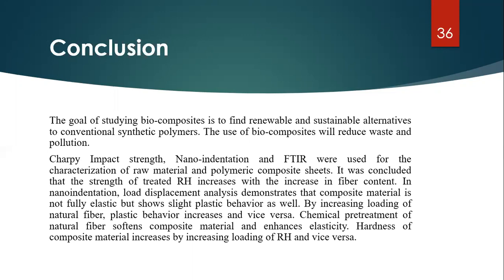It was concluded that the strength of treated rice husk increases with the increase in fiber content. In nano indentation, load displacement analysis demonstrates that the composite material is not fully elastic and shows slight plastic behavior. By increasing loading of natural fiber, plastic behavior increases, and by decreasing loading, plastic behavior decreases. Chemical pre-treatment of natural fiber softens the composite material and enhances elasticity. Hardness of the composite material increases by increasing loading of rice husk and vice versa.